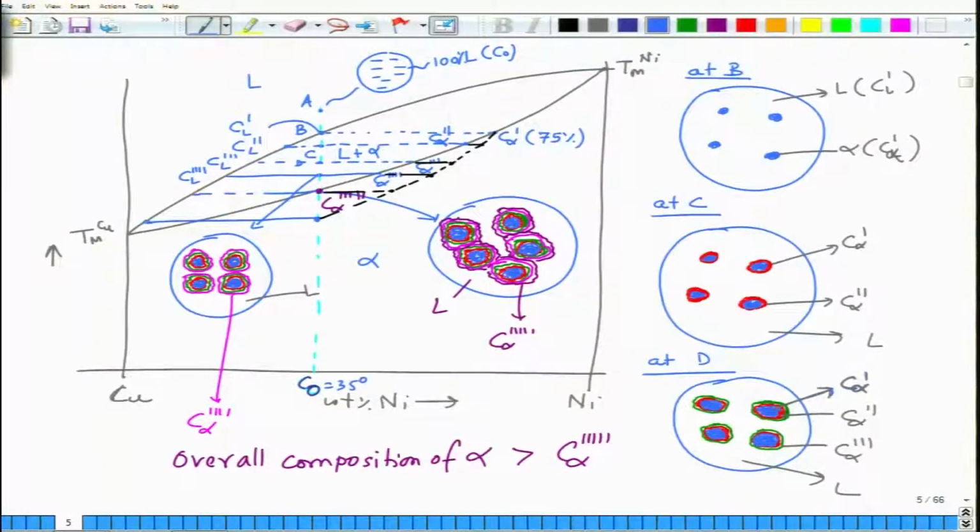So you will have some solid and this will be the last liquid to freeze. So this is the extra degree of cooling that one needs to provide because of inhomogeneous compositions, because of non-uniform cooling, because the solidus line has shifted from here, from there to here. So this is the shift of solidus line that you will obtain, and as a result you will have liquid present in the microstructure not until this point, but until this point. So this produces a microstructure which is very inhomogeneous, and that is why one needs to carry out heat treatments, etc., to further homogenize the microstructures.